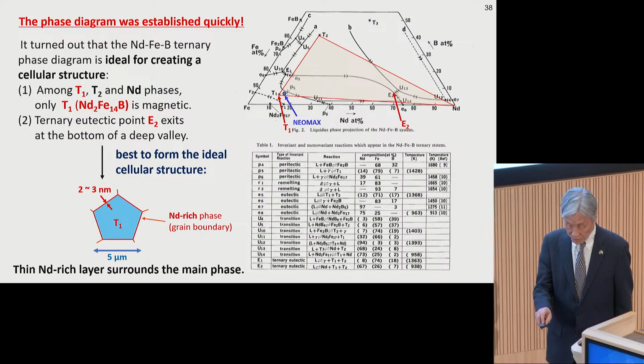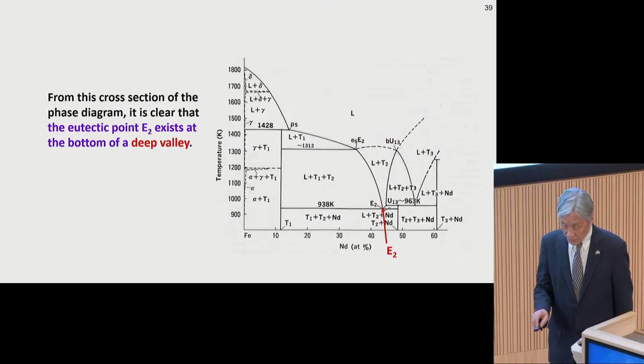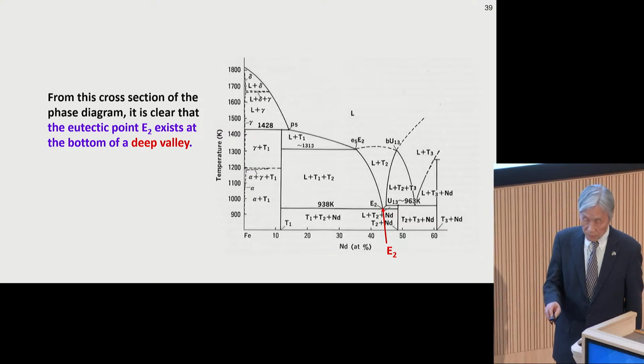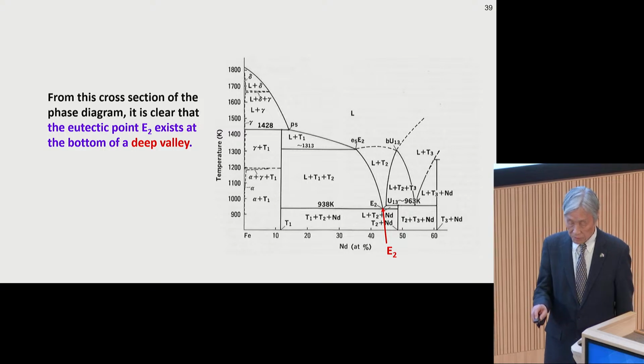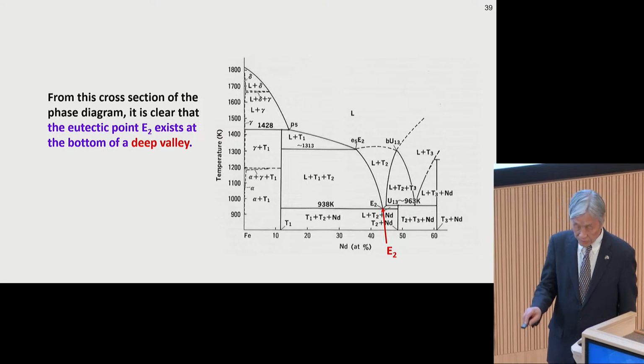And what is necessary is the thickness of the boundary phase is thin and non-magnetic. And this is realized by the fact that the E2 is very deep. Therefore, by this phase diagram, we have very good magnetic properties. And also, it's easy to see. From this cross-section of the phase diagram, it is clear that the eutectic point E2 is very, very deep at the bottom of the deep valley.